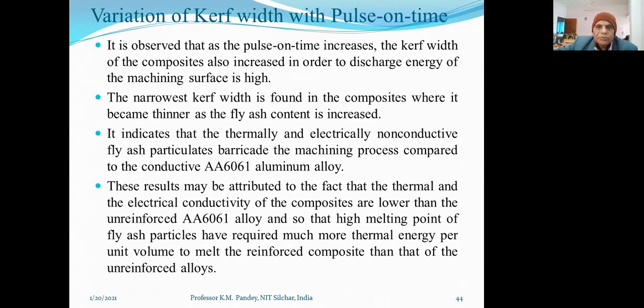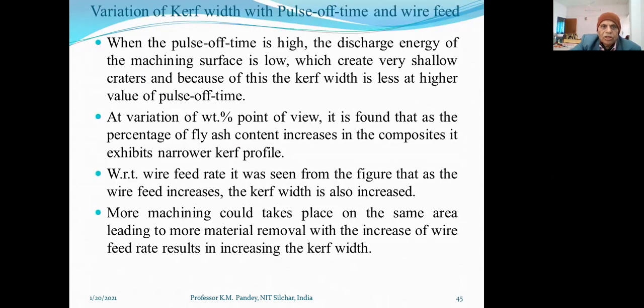Then the narrowest kerf width is found in the composite with more fly ash, as it became thinner as the fly ash content increased. It indicates that the thermally and electrically non-conductive fly ash particles obstruct the machining process compared to the conductive A6061 aluminum alloy. These results may be attributed to the fact that the thermal and electrical conductivity of the composites are lower than the unreinforced A6061 alloy, and the high melting points of the fly ash particles require much more thermal energy per unit volume to melt the reinforced composite than the unreinforced alloy. So this is another conclusion of this experiment about kerf width.